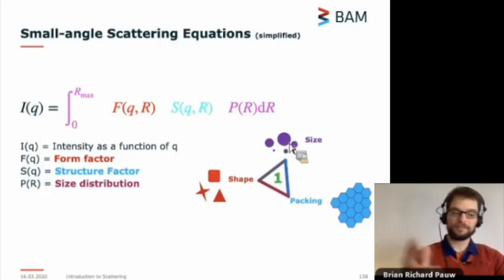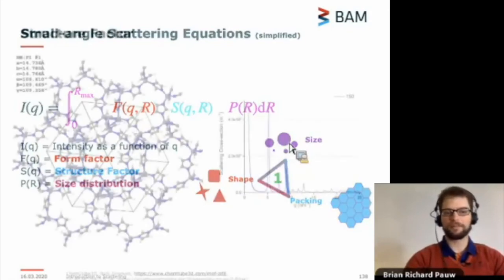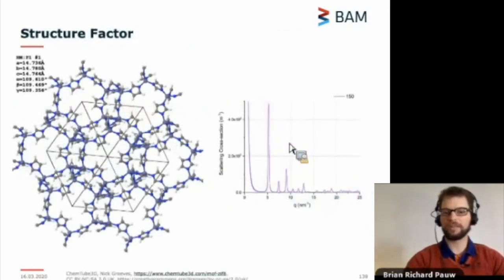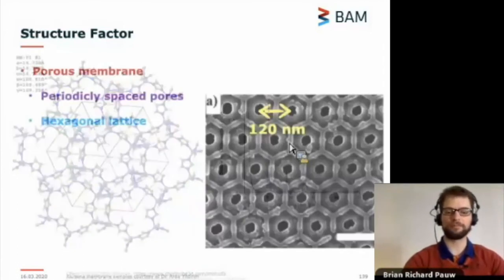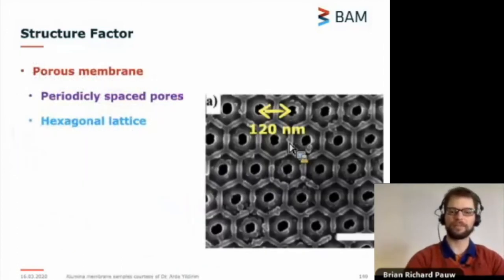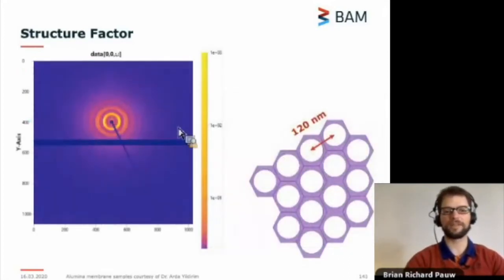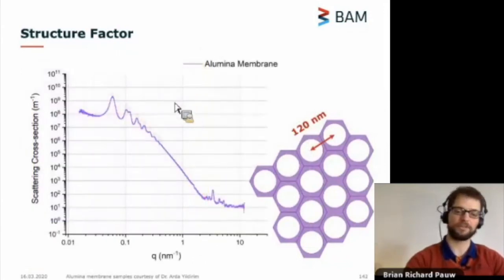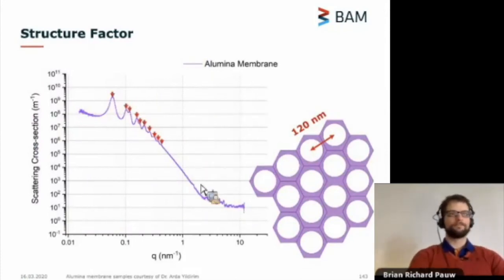You've seen the structure factor just now, these regular distances that we have, but they don't just appear at the wide angles. They can also appear at the small angles. For example, for this alumina membrane that we measured, with pore spacings between the pores in a hexagonal array of 120 nanometers. This means that at our longest distance, where we've measured larger structures, we still see diffraction peaks, and we can analyze these, and they will give us the peaks for a hexagonal structure spaced 120 nanometers apart.